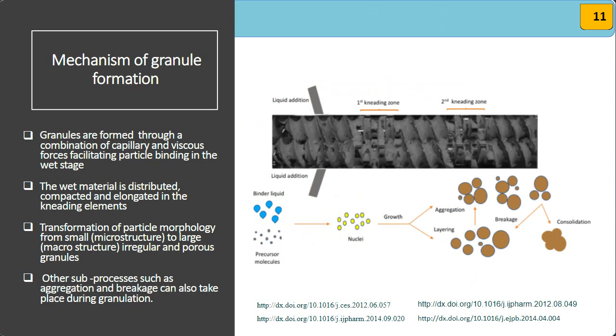The next part of the presentation is related to the mechanism of granule formation. Usually the granules are formed through a combination of capillary and viscous forces, facilitating particle binding in the wet stage. The wet material is distributed, compacted and elongated in the kneading elements, and eventually the transformation of the particle morphology from small to a large, irregular and porous granule takes place. Other sub-processes such as aggregation and breakage can also take place during granulation.